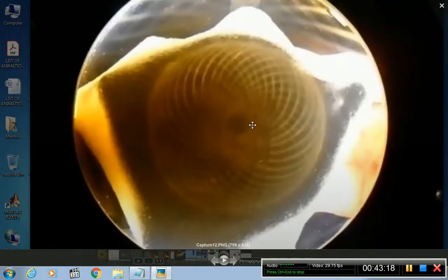Here, where the hole is, it doesn't mean that there are no magnetic flux lines. On the contrary, here the magnetic flux lines are the most dense, but because they are going totally vertically in, the surface of the nanorods is minimized, and therefore we get minimum to zero light scattering. So that's why we see the area black, but it doesn't mean that this area is void of magnetic flux. It is full of magnetic flux, and actually it's the most dense magnetic flux.